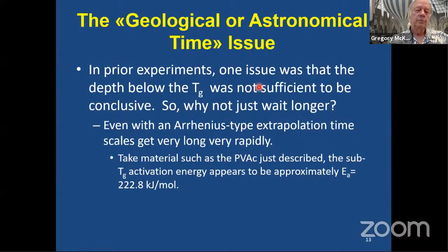So the geological time or astronomical time issue is in these prior experiments. One issue was that the depth below Tg wasn't sufficient to be conclusive. We're only 15 degrees below Tg, and the Kauzmann temperature is maybe 50 or more degrees below Tg. So we're not very far towards the Kauzmann temperature, the point of divergence.